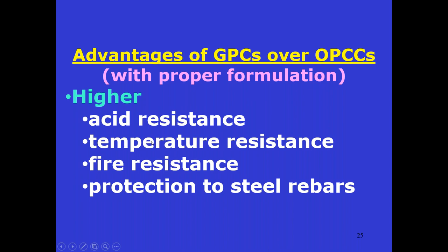And temperature resistance. This I want to clarify more here. Temperature resistance is equal to ordinary concrete for general formulations. But if you make the formulation proper, I'm using the word proper, then only you will get high temperature resistance. So whatever Davidovits has worked with, he worked from a ceramic point of view. That's why all his geopolymers always have fire and temperature resistance, not with us in India, because we use mostly fly ash and GGBS, sometimes metakaolin. And this will not produce temperature resistance. It has to be formulated properly.